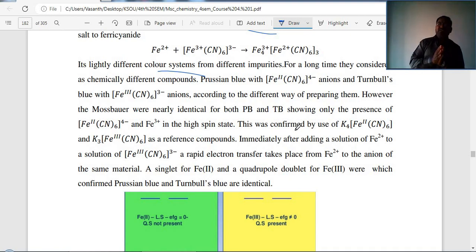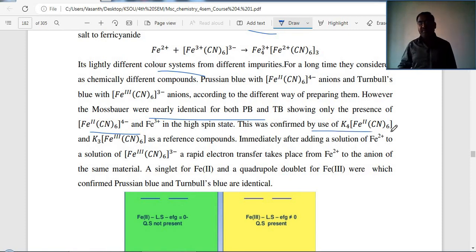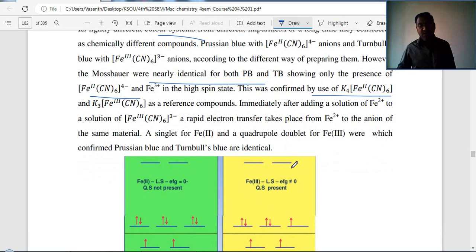According to the different ways of preparing them, however, the Mossbauer spectra were nearly identical for both PB and TB, showing only the presence of Fe(CN)6 4 minus and Fe3 plus in the high spin state. This was confirmed by use of potassium hexacyanoferrate(II) and potassium hexacyanoferrate(III) as reference compounds.